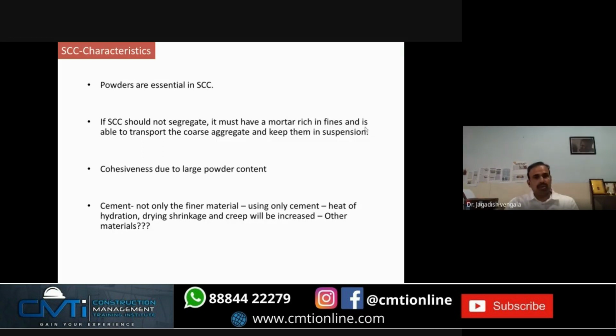So if it has to maintain homogeneity, keep the coarse aggregate in suspension, and transport the coarse aggregate from the point where it is poured to the other point, it should have a rich mortar. And this cohesiveness you can achieve due to the large powder content, that means between 450 to 600 kgs. When you look into IS 456, the cement restriction is 450 kg per cubic meter. If you are using only cement, you end up with heat of hydration, drying shrinkage, and other problems.